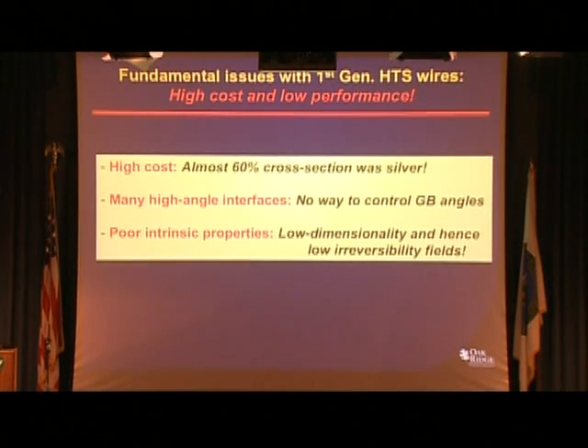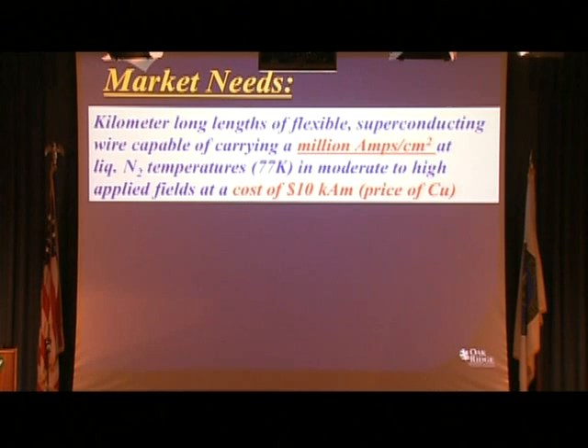So here are the real problems with the first generation wires. High cost of silver. 60% of the wire was silver. It had low performance because no way to control the interfaces. And as I mentioned previously, these are more two-dimensional than YBCO and had poor intrinsic properties to begin with. So the market needs for superconductor applications, we need at least 1 million amps per centimeter squared, 77 Kelvin, at the price of copper that you can buy in the hardware store.